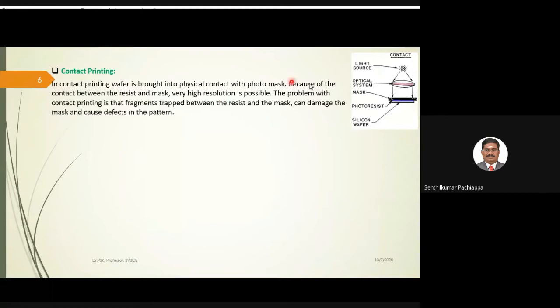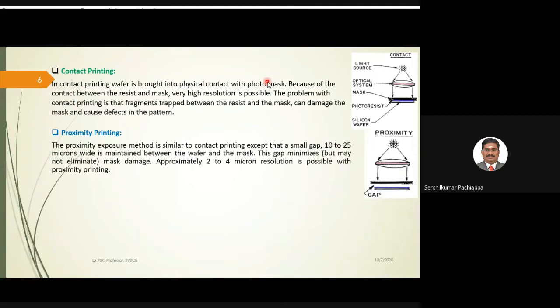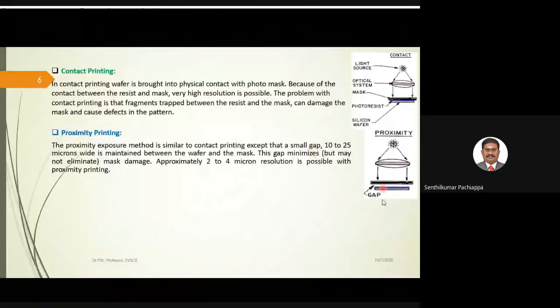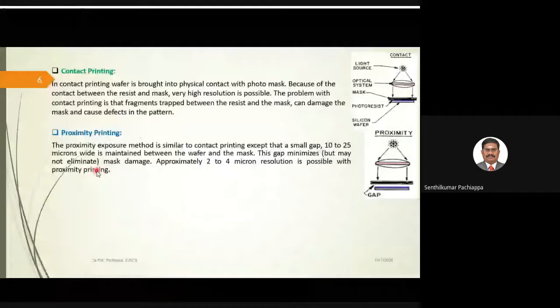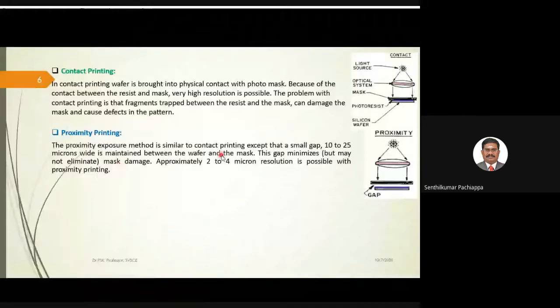Next one is the proximity printing. The proximity exposure method is similar to contact printing except for a small gap. A gap of 10 to 25 microns is maintained between the wafer and the mask. This gap may be minimized but not eliminated. Approximately 2 to 4 micron resolution is possible with proximity printing.